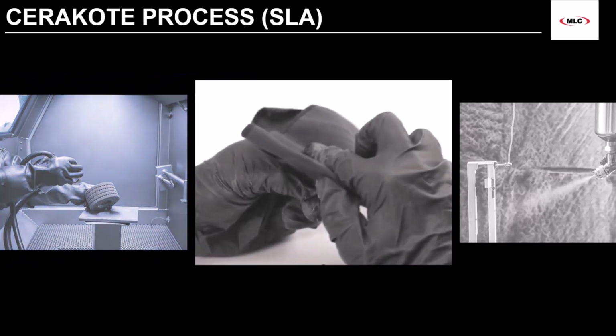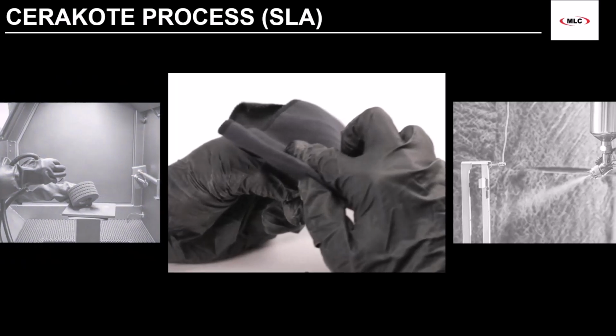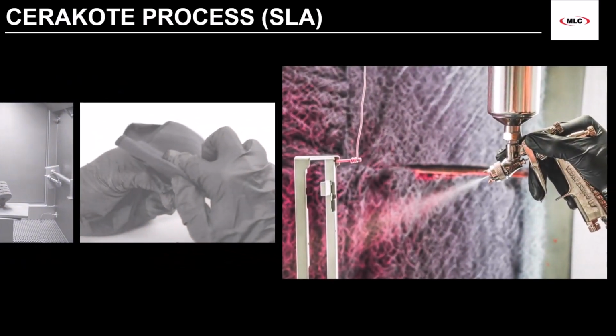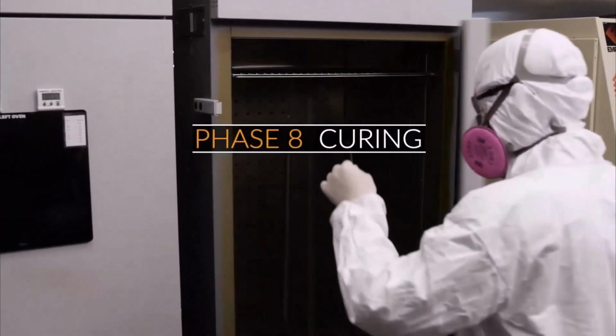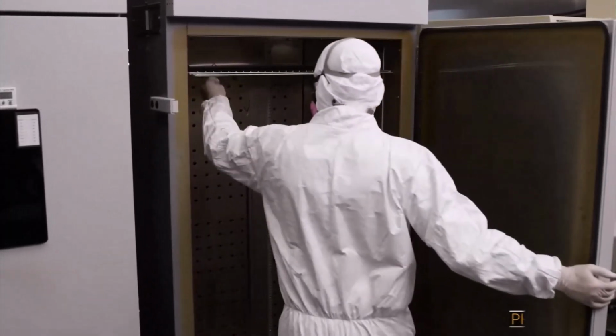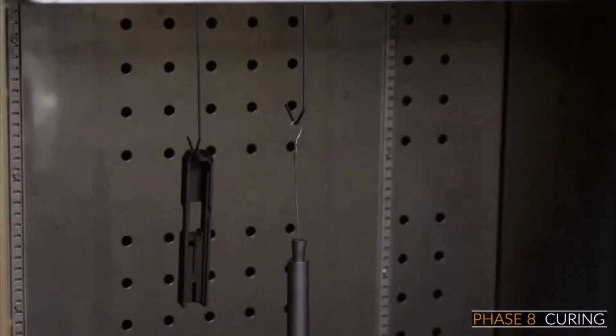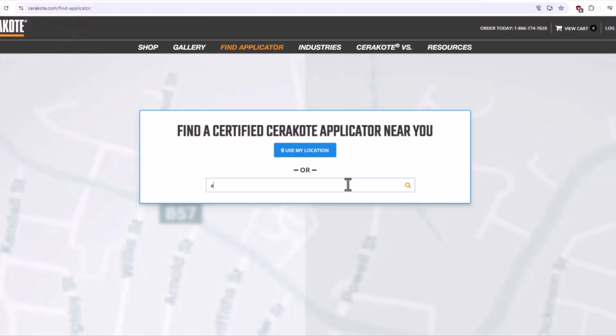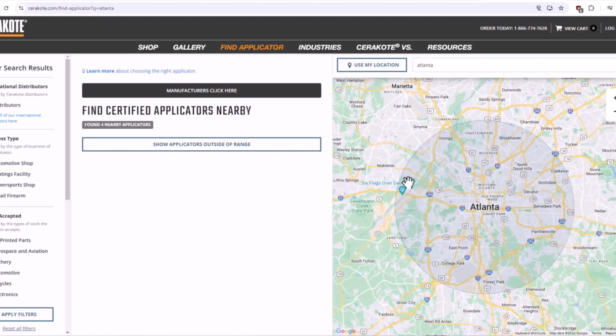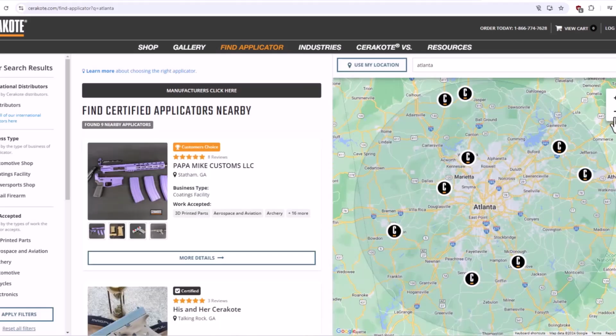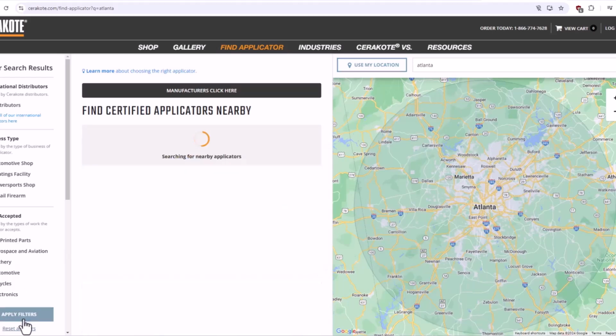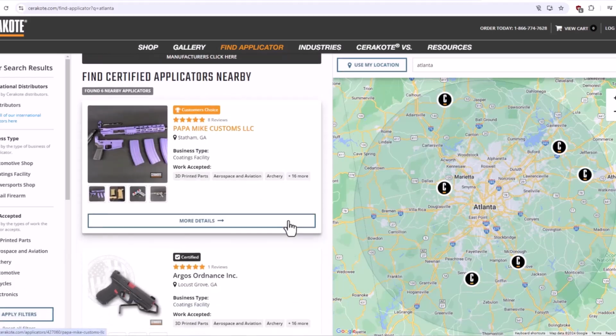The process involves media blasting the part with 100 grit aluminum oxide or garnet sand at 40 psi to etch the surface for adhesion promotion. The part is then wiped down with a cleaner, and then the part is Cerakoted via a spray applicator. This helps achieve the thin film description. Once uniform coverage is achieved, the part is post-cured at an elevated temperature or air-dried in ambient conditions. For most of you, this information is totally irrelevant as MLC has a list of approved applicators. These guys have all the equipment and experience and are happy to help you get Cerakoted parts.